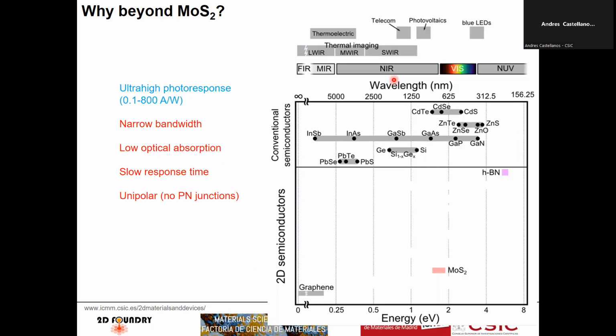This is very important because for each application, you have just a window of wavelengths where you optimize the material. So if you want to do thermoelectrics, you will go to this family with lead, for example lead selenide, lead sulfide, or indium arsenide. If you want to do photovoltaics, then you have this window here that optimizes. Silicon is slightly out of the window that optimizes photovoltaics, but it's close enough. So there is a take-home message.